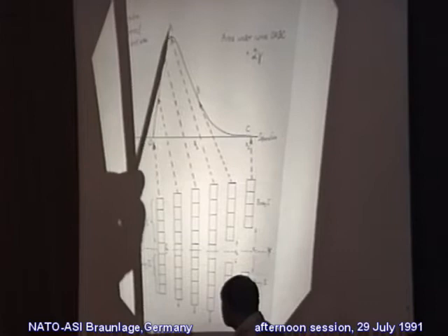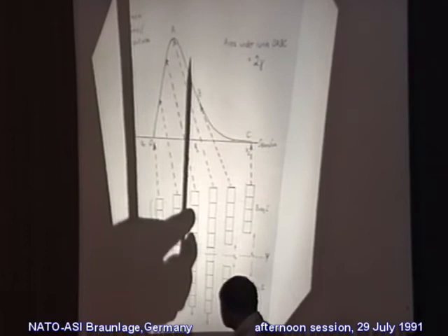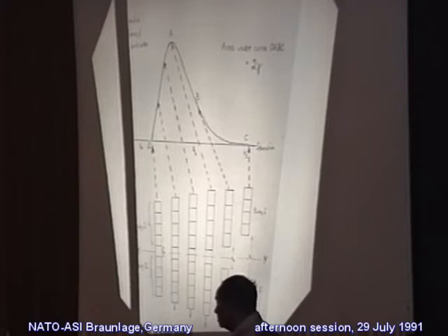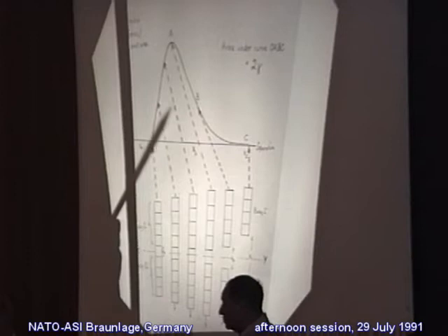Once you come to this point here, the system is actually softening, and the natural tendency would be for it to release. This is the essence of the jump technique, which was popularized by yourself, Jacob. It would be very difficult, if not impossible, to undertake an experiment in this regime. So my belief is that if you could do the experiment, then you would construct this curve in a stable way. Of course, the uncertainty principle would prescribe that it would be possible for the interface to fail immediately and catastrophically, but in truth it wouldn't. So I think Professor Tabor alluded to the point that it is a necessary artifact associated with the way that these measurements are done. There'll always be elasticity in the transducers or in the subsurface regions.